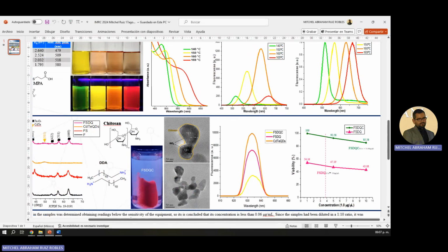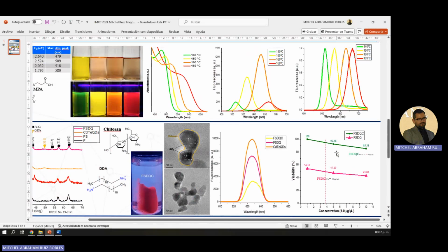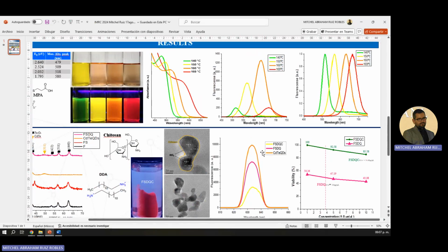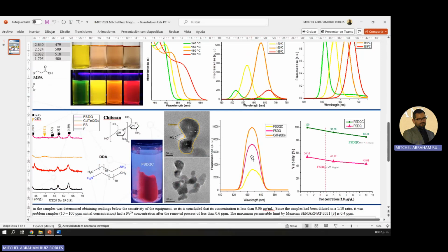By fluorescence, we observe the wavelengths of the luminescent peaks, which reach the maximum for each sample quantum dot peak, and the bare quantum dot's luminescence decreases as the layers increment in the final nanocomposite, resulting in a reduction, shown here, of luminescence of about 30% of the bare quantum dot's fluorescence.